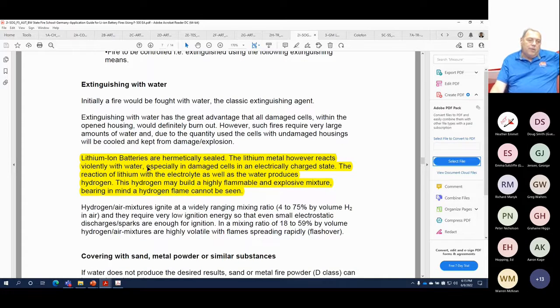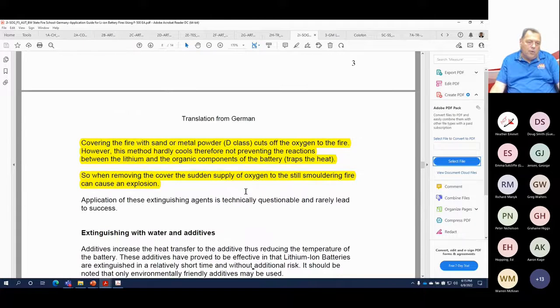So some of this came from the Bosch testing on lithium-ion battery with plain water. The issue there is they sometimes get a reaction depending on the chemistry of the battery, and as we know, it takes copious amounts. Covering the fire with sand or metal cuts off the oxygen. However, this method hardly cools, therefore not preventing the reaction between the lithium and organic components. So when removing the cover, we suddenly supply oxygen and we still have a smoldering fire.